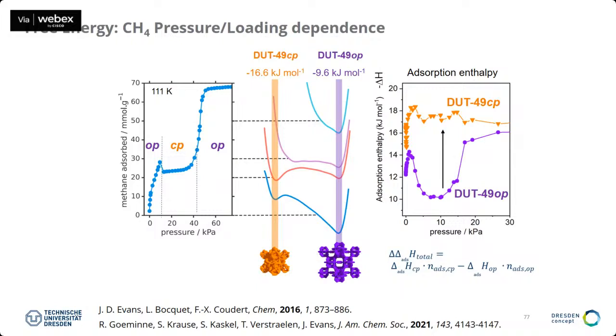So when you calculate the energy, this is the open pore form, this is the contracted pore form. If there's no gas present, then the open pore form is the energetically favored form, basically here. And you don't want to contract because this biphenyl strut is very energetically deformed, and this is not favorable. But when you increase the pressure, when you dose gas to it, there's an energetic gain because there's a higher adsorption enthalpy for the small pore as compared to a larger pore. And if this large pore of 2.4 nanometer is contracting to only 1 nanometer, there's an energetic gain. In other words, the methane feels more happy in a small pore, and this releases energy to the outside. And that's the driving force. This is the higher adsorption enthalpy for the contracted pore phase.